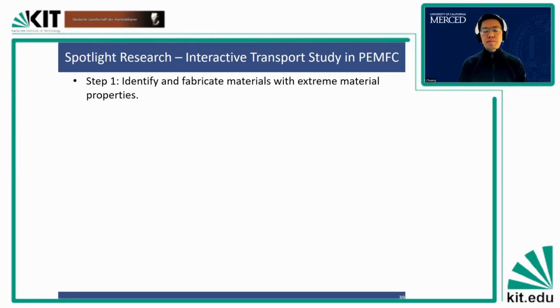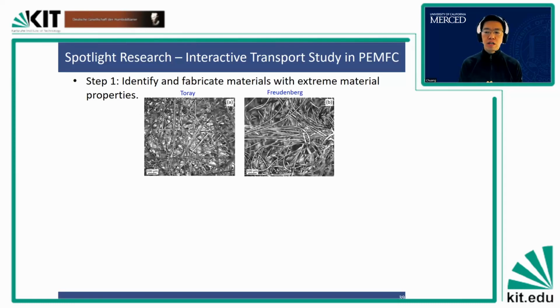The first step is that we identify and fabricate materials with extreme properties. Remember I showed you this. There are 2 different ways that we can produce this gas diffusion layer. On the left-hand side is the wet lay process, on the right-hand side is the dry lay process. For the wet lay process, because it has this chemical resin, in order to carbonize it, this material is usually graphitized at a much higher temperature, roughly about 2000 degrees C. Some of them can be as high as 2400 degrees Celsius.